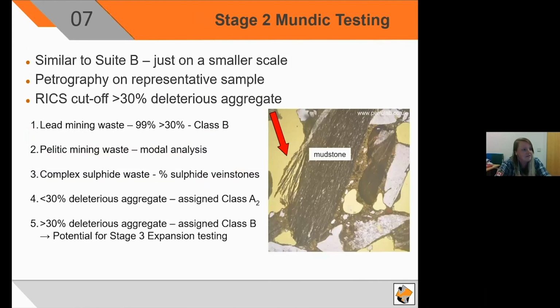So for further testing after the stage 1, you go on to the stage 2, which is essentially the suite B process, just on a smaller scale. We do petrographic analysis on a representative sample, and as deemed by the RICS guideline, we have a 30% deleterious aggregate cutoff. So anything less than 30% is deemed good aggregate, and greater than 30% is deemed bad aggregate. To put it into perspective, the worst aggregate down here is the lead mining waste. 99% of the time, it has greater than 30% deleterious aggregate, and therefore is Class B as standard.